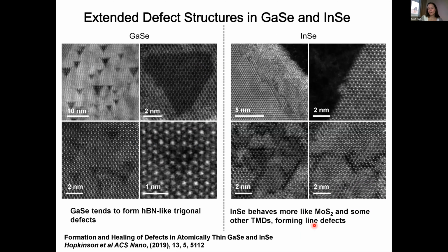Differences are again observed in the larger scale defects. We see these triangular type defects, a little bit like we get in hexagonal boron nitride. We see these triangular defects in gallium selenide, whereas indium selenide has a more molybdenum disulfide type defect structure, these long strings of defects. In molybdenum disulfide, that's because the sulfur defects dominate. So here we're going to assume that it's the selenium defects that are dominating, giving us these line defects, and that fits with what we can see in the simulations.